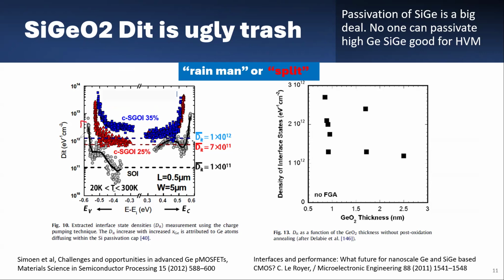Let's look at the comparison in terms of defect density. It's 2 orders of magnitude higher. This means that your mobility sucks, because your carrier will see the defect number. So anything above 5E10, you are in deep trouble. If you are in E11, you are probably okay, but risky. This is where the current TSMC Intel sit. Anything higher than E11, you will have a big problem, I'm telling you, okay?